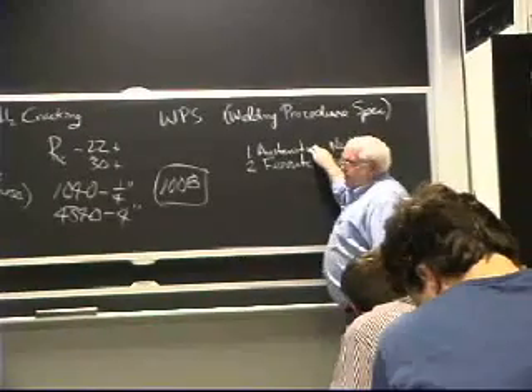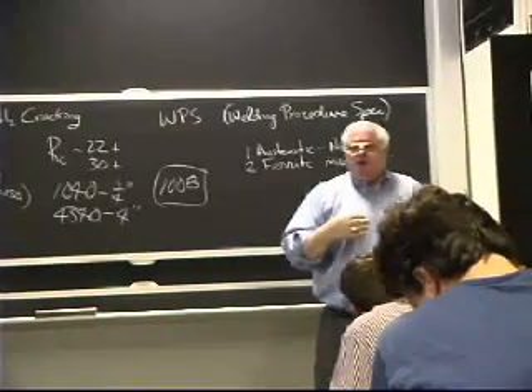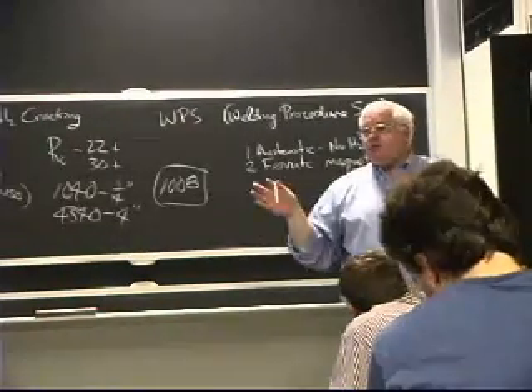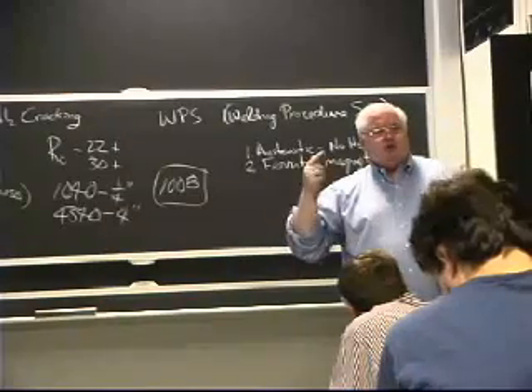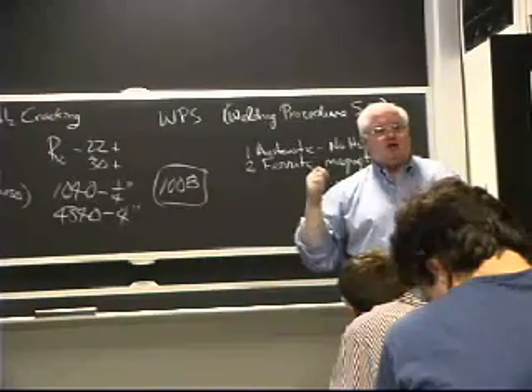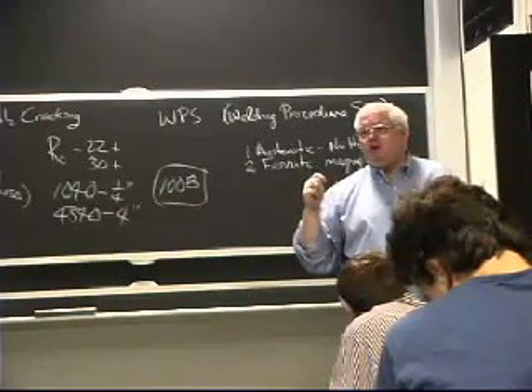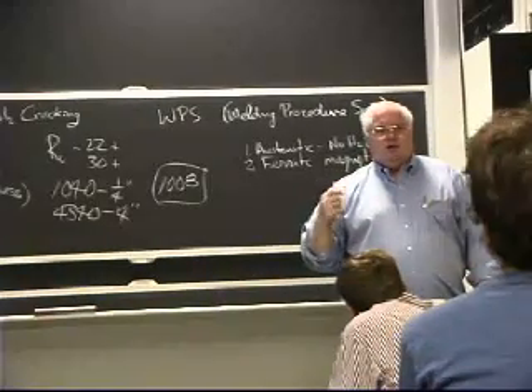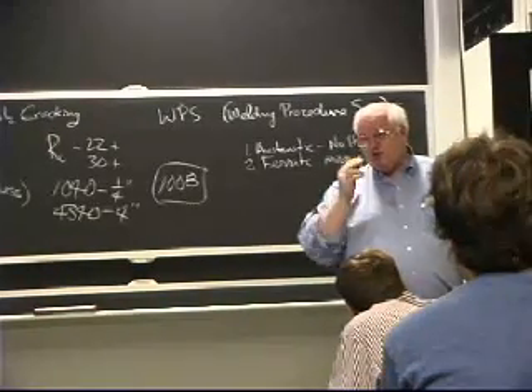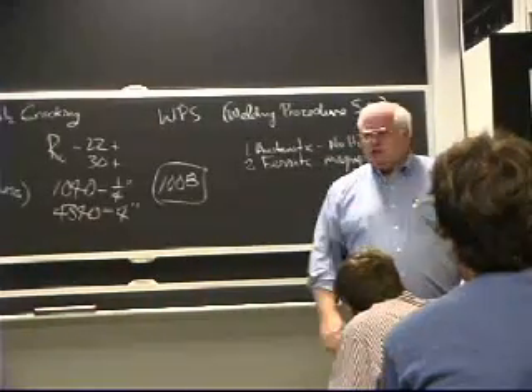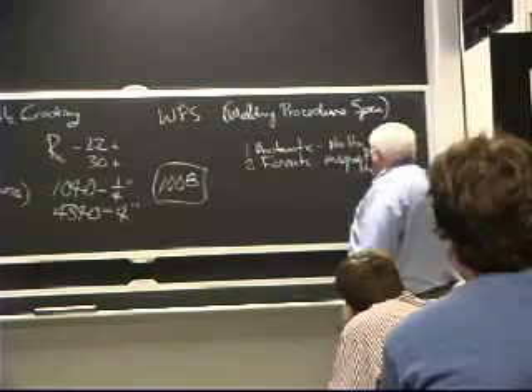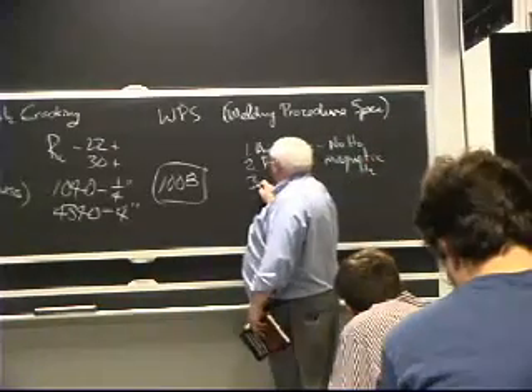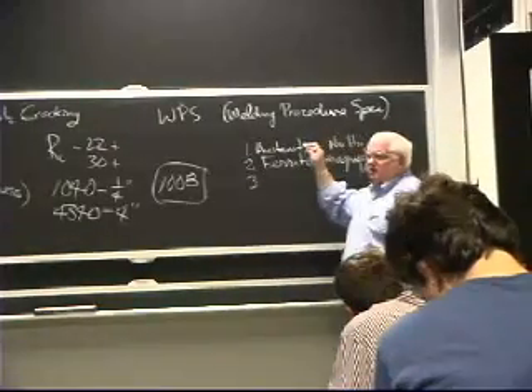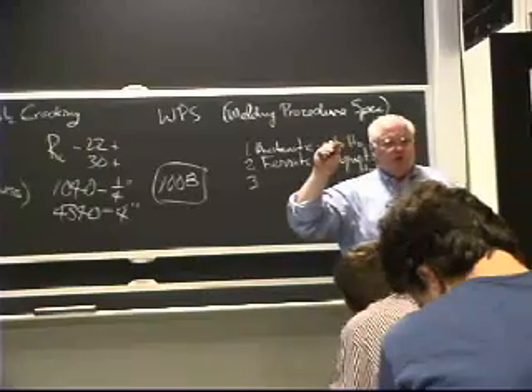In fact, one of the solutions when you're having a hard time welding carbon steels without hydrogen cracking is to use austenite filler metal, because the austenite dissolves lots of hydrogen and holds it in. It has like 10 times the solubility for hydrogen and doesn't release it into the base material where the cracking usually occurs.